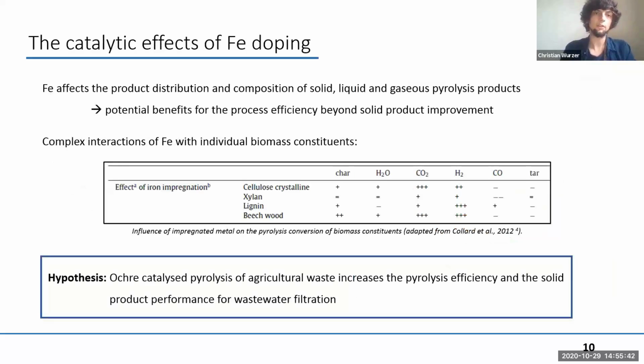But iron is not only enhancing magnetic properties, but it also affects the product distribution and composition of your pyrolysis process. So you change the pyrolysis yield distribution between solid, liquid, and gas fraction, which enables potential benefits for the process efficiency if you are able to estimate which fraction you can enhance and which one you can decrease in amount produced. And to give you an idea about the complex interactions of iron with the individual biomass constituents, there's a table from Collard et al.